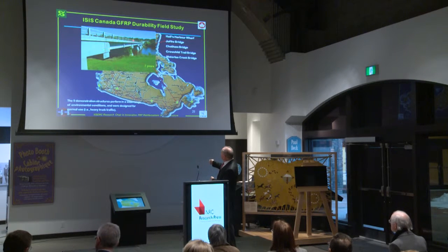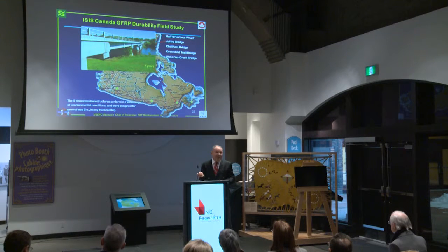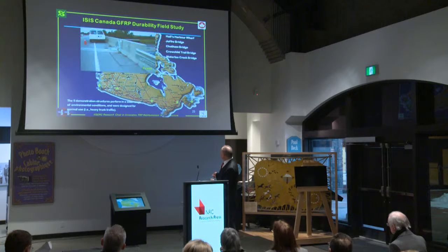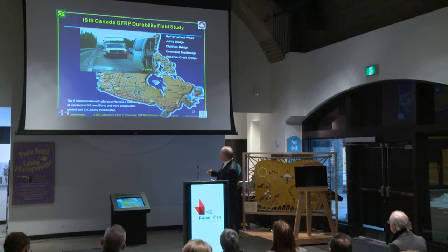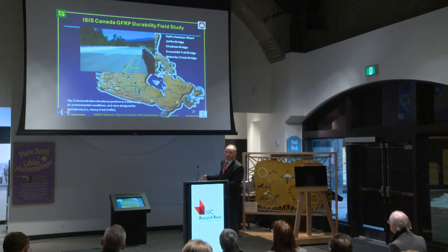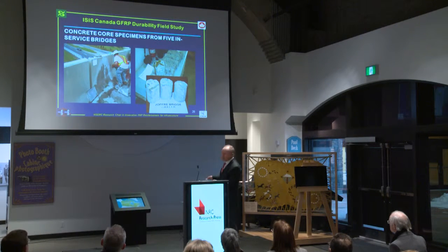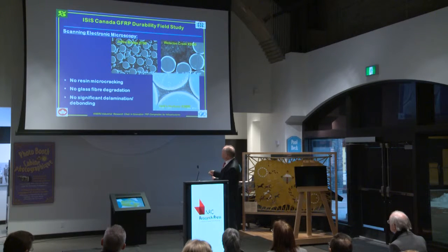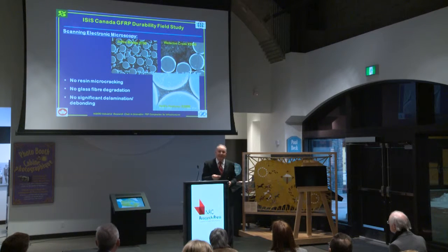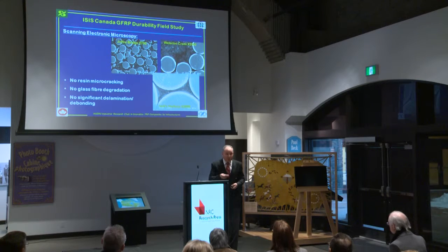There is here Joffre Bridge. This is the first bridge in North America, including Canada and US, that I did in 95, which is close to 20 years now. Also here in Chatham in Ontario, in Alberta, and in British Columbia, so all across Canada. We went there and took cores from these bridges, including this material, and looked at how this material that we implemented in the field is now behaving in the in-service environment. And we found that this material has no degradation. So we introduced it in the code based on this field research.